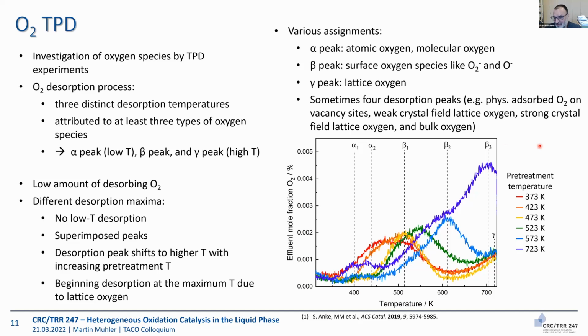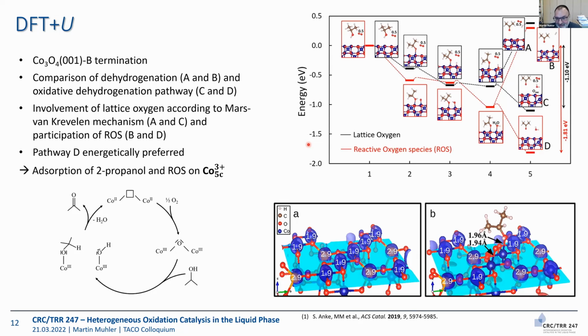Gamma, that's then for sure, that would be at even higher temperatures where you just by heating can convert Co3O4 back to cobalt monoxide. That would be then a phase transition. It's the lattice oxygen that is released at the highest temperatures, and the other species must be atomic oxygen or surface oxygen species like superoxide or O-. But what we still can do, we can integrate and correlate. Then, of course, we ask our colleagues from theory for help. In this case, that's Rosica Pencheva and her group.